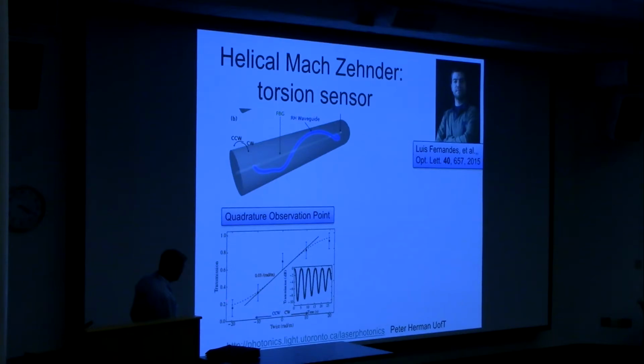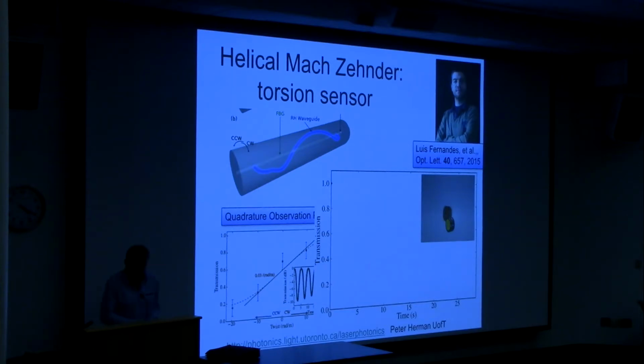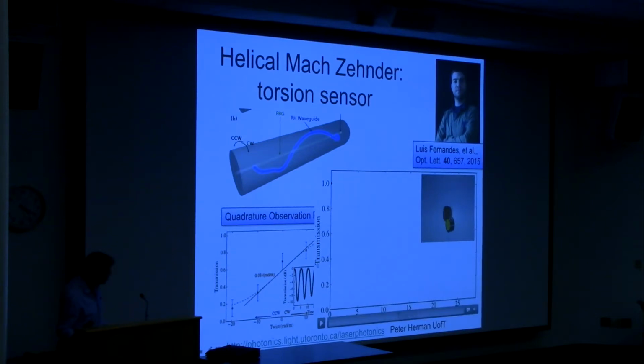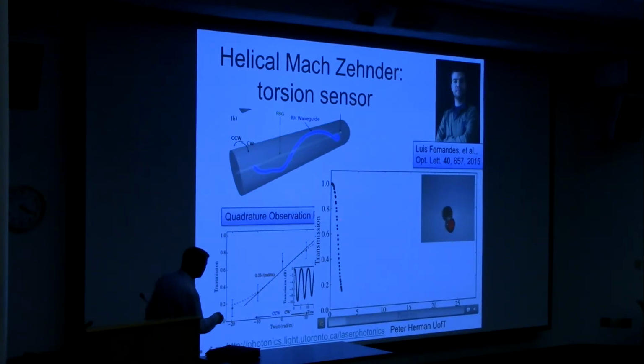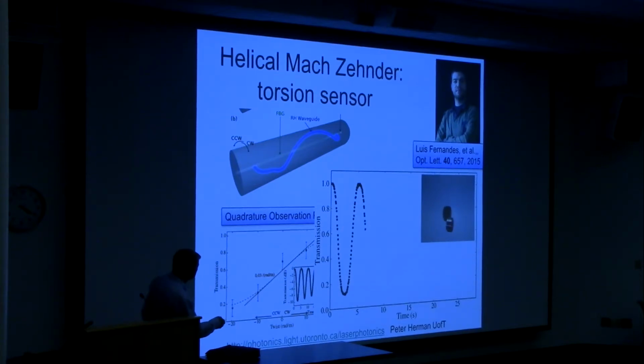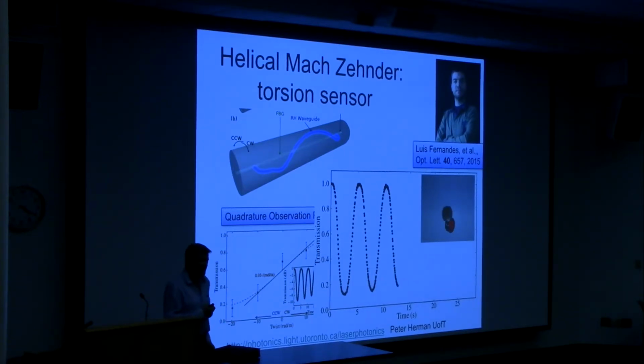So what we do is we go to the quadrature point and sense here, and then here's a little picture of this fiber suspended by magnets. So what we do is we twist the magnets, and then we record the light at the quadrature point. And as the helical path tightens up or relaxes, it shifts the wavelengths, meaning the intensity is shifting. We record that, and so we now have a directional torsion sensor for the first time done in a single fiber. So that's really convenient to build in a single device this new kind of sensing arm that was only done with multiple fibers before.